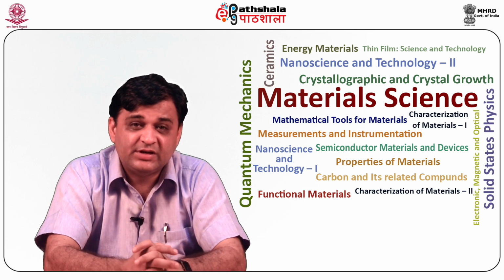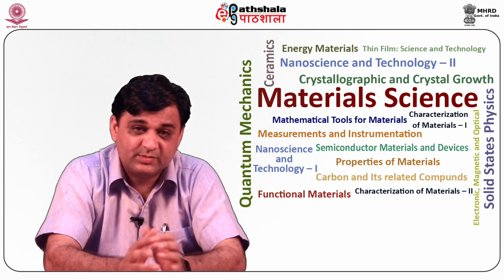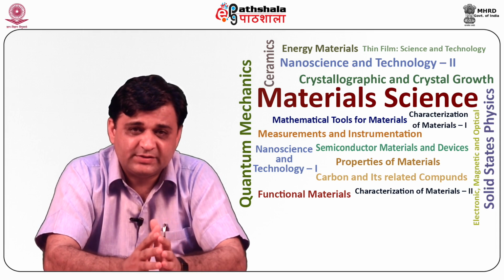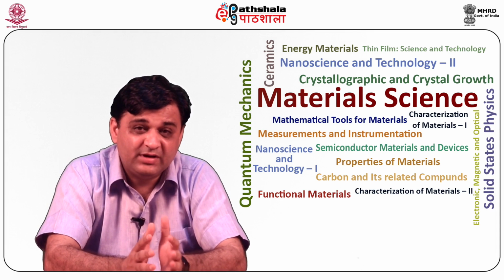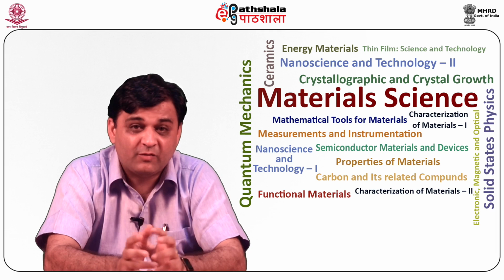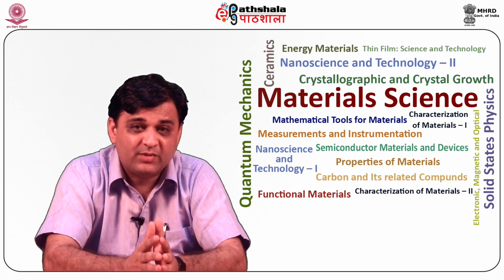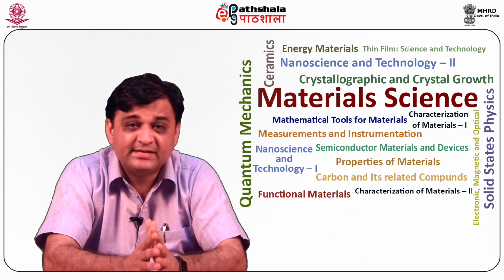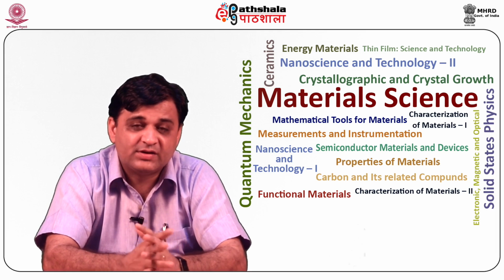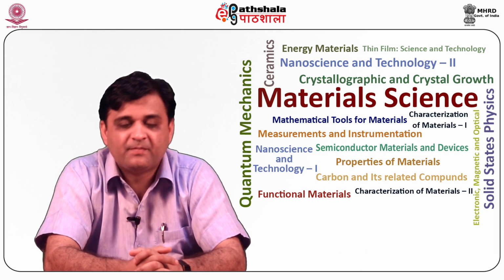Also, this is a non-destructive technique, especially for hard condensed matter. But if the beam intensity is high, it can be destructive for polymers and organic systems, so we have to be careful. By minimizing the intensity, we can make it non-destructive for organic systems also.